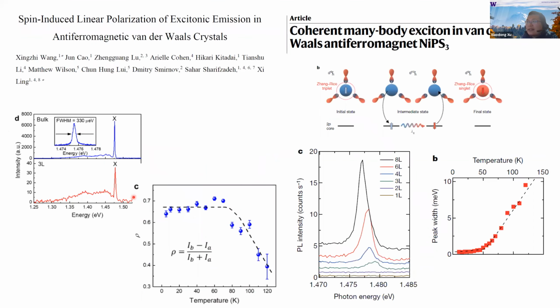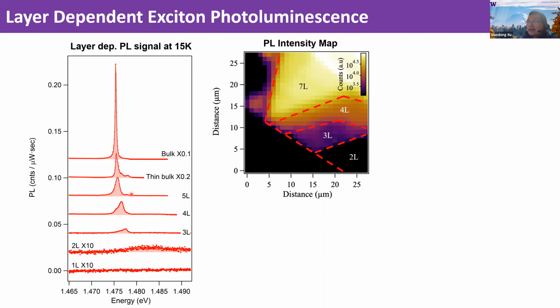Also, this represents the layer thickness dependence. The other thing you can see is that from layer thickness, when I go to very thin, the width gets really broad. One of the reasons is that when you go to really thin layers, the spin fluctuation gets stronger. So that's another possibility, but that's all speculation, because there could be some other magnetisms when I go thinner. That's right. So maybe the power dependence can tell how large these excitons are? Actually, we did that, and we don't see a significant, appreciable width dependence. Yeah, those are excellent questions. I think we would like to know the answer to. Okay, that's wonderful. Thanks.